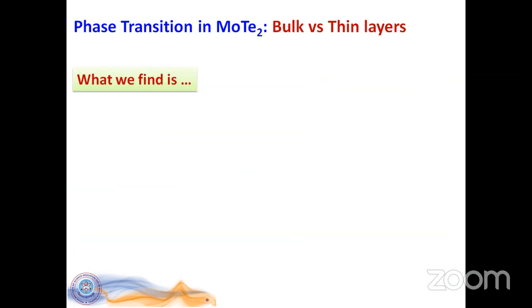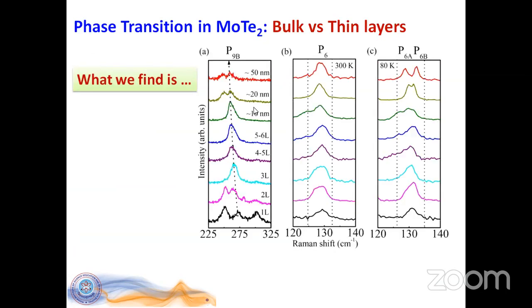Now let's see what we find. So here are data for various thicknesses, starting from the reasonably thick, which is about 50 nanometer. And if I remind you, for 50 nanometer, they show that there is a phase transition across the temperature. And then 20 nanometer, 10 nanometer, and then we have these various thicknesses. And these thicknesses we get based on the Raman signature of this mode, and there is one more mode. And based on the shift of those modes, we can very nicely estimate the number of layers of that sample.